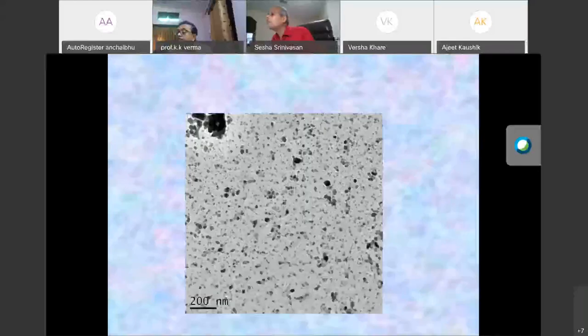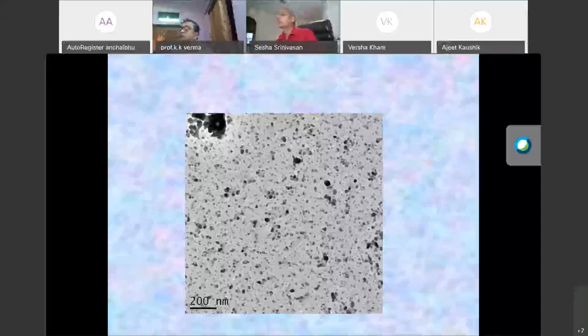You see, if you magnify more, you can see there are white patches. It means the formvar is broken, and there are small patches where this material is. And if you zoom in again, then you will end up getting these nanoparticles, very nice nanoparticles of any material which you want to see. So you can see the magnification is very, very high here. You can go up to see even the atoms and the small things.